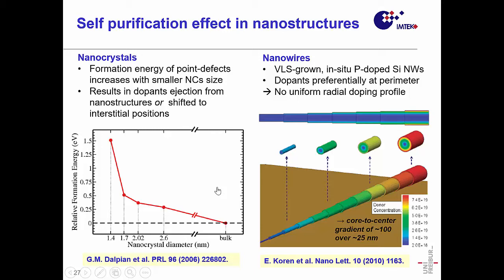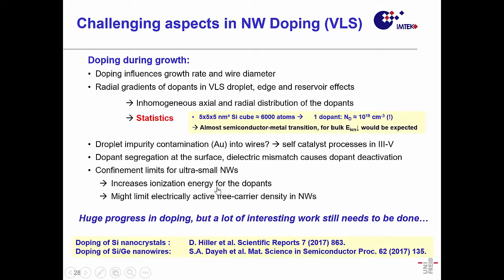You have this liquid droplet where you feed your materials in to have an alloy, and then it's pushing out and growing the nanowire. What happens if I now put an additional atom into this? You're changing the alloy concentration, and with that you're changing the surface energy. That means your droplet might be more de-wetted or more wetting your wire, so you're changing the size of the wire. And what you also see, and that's shown in literature, is that you're not getting a uniform radial doping profile anymore. That gives you some problems, of course, for having devices in a good way.